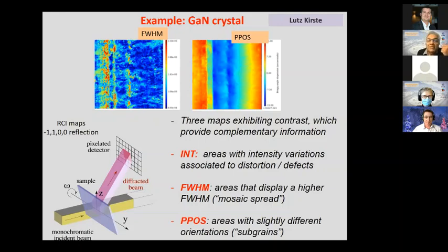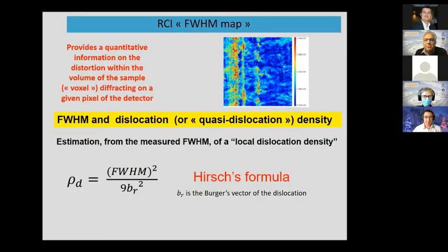On the full width half maximum map, you have areas that display a higher full width half maximum. We can say that this is mosaic spread, and this higher full width half maximum corresponds to defects, defective regions. And on the peak position map, we have areas with slightly different orientations, in this case, subgrains. Let's go more in detail to each of these maps.